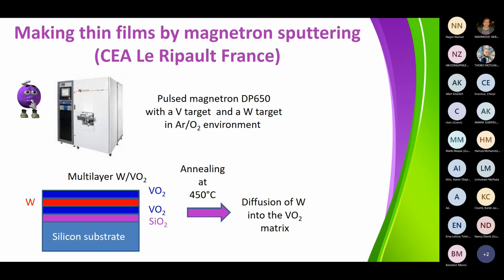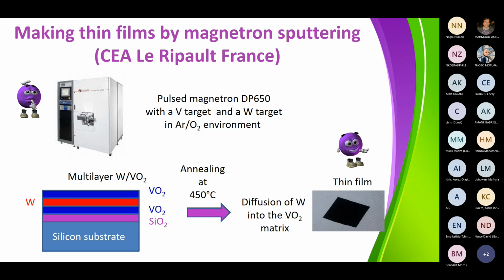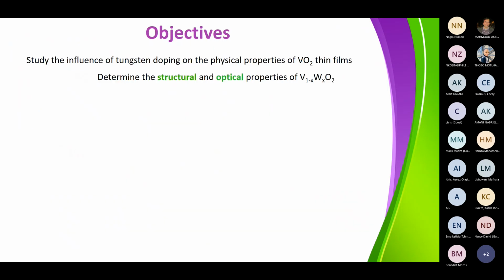And then the next step was to anneal those materials at 450 degrees Celsius, so that there was a diffusion of tungsten into vanadium oxide. And in the end, we were observing a thin film, well, which was normally homogeneous in terms of the repartition of tungsten inside the vanadium dioxide.